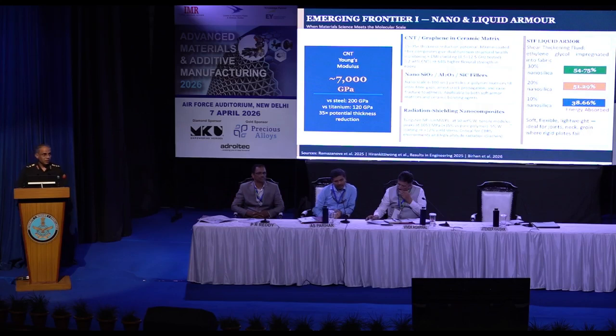STF, liquid armour, is also one field where a lot of work is happening around the world. A nano-silica suspension in ethylene glycol impregnated into textile flows freely normally, and solidifies when the impact happens. 30% nano-silica loading gives 84.75% more energy absorption. These figures in green, yellow and blue are the energy absorbed values. Operational significance: you can put STF everywhere a rigid plate cannot go. Collar, groin, deltoid joints, etc. This is the engineering answer to the Ukraine coverage lesson that I brought out.